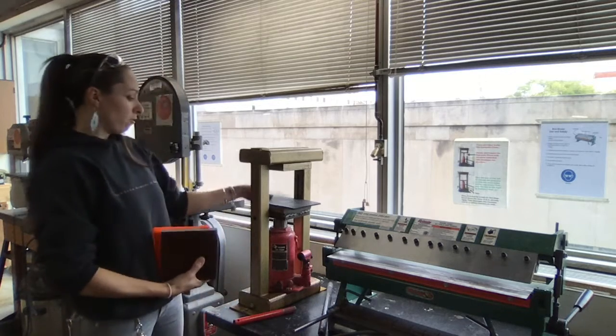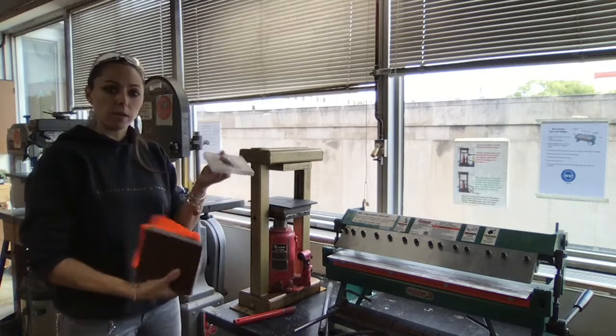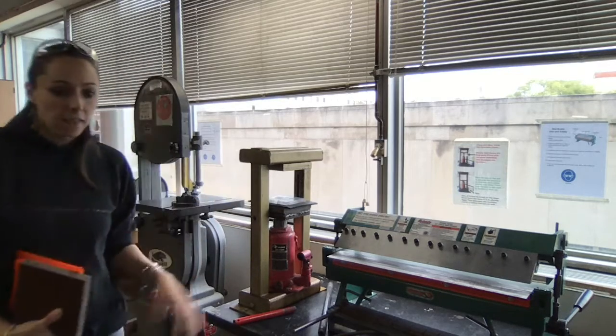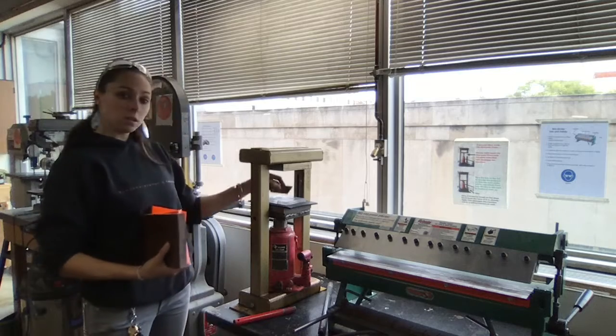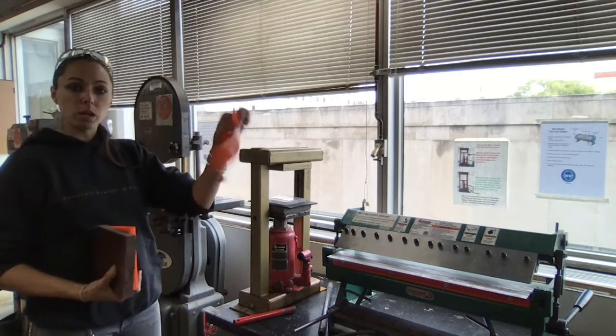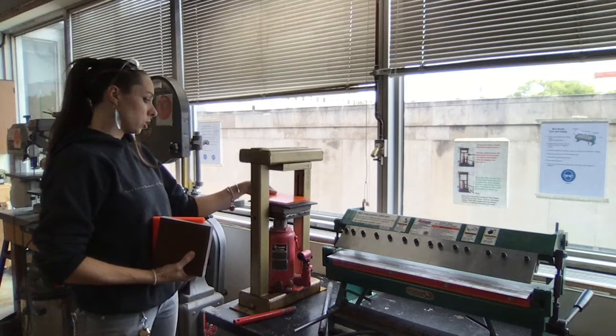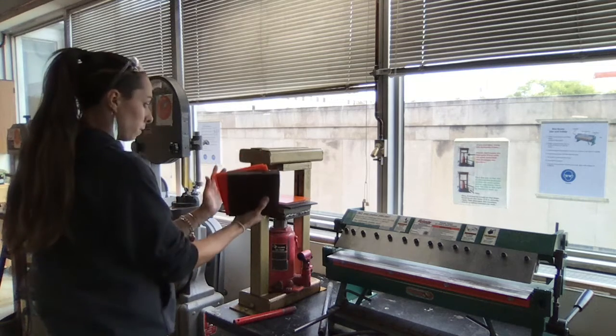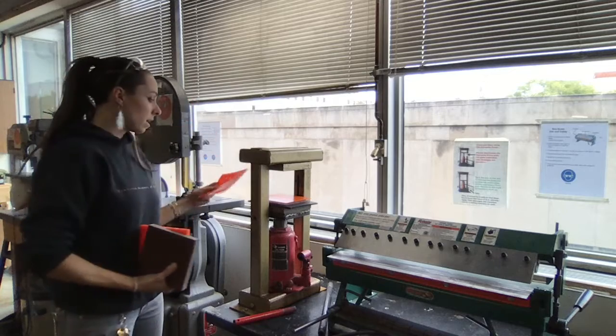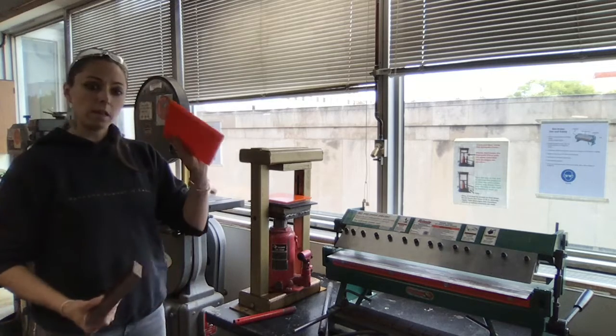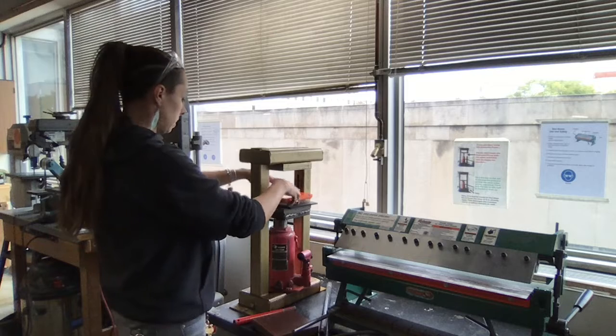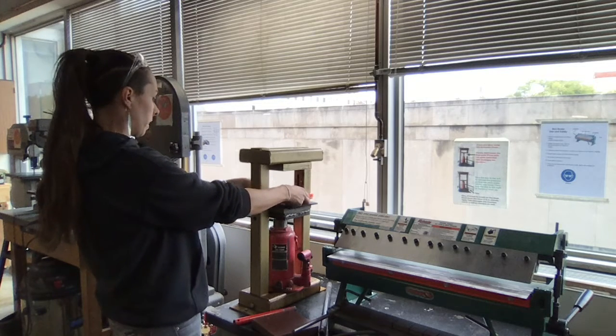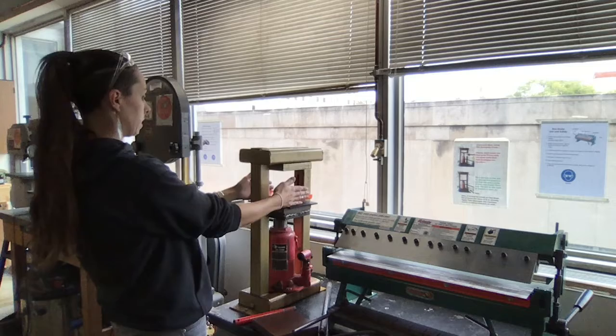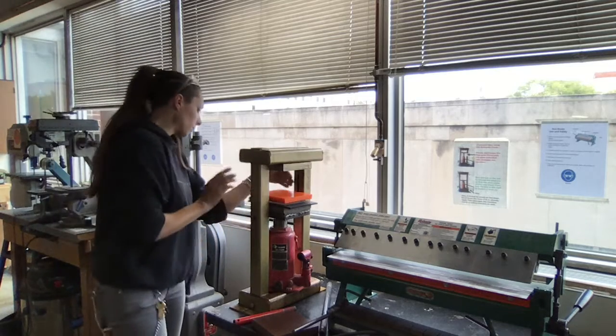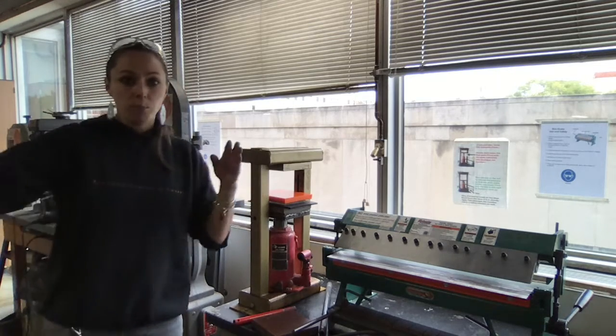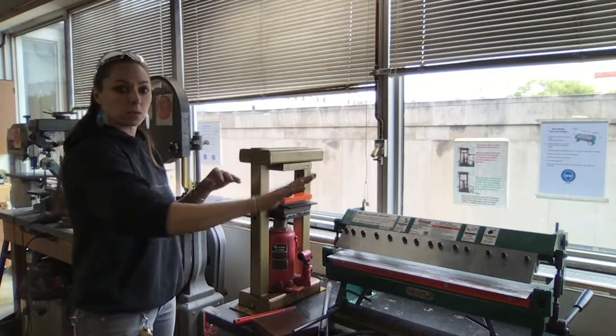So after I have my piece of recycled rubber down, I'm going to go ahead and put my die down. And then I'm going to put my annealed metal down. Then I'm going to put the 1/16 of an inch durometer down, and I want to make sure it's perfectly spaced in the middle. Then I'm going to put my 1/8 inch, then my 1/2. And this is another good time to always evaluate, is this in the center? Is everything lined up perfectly? You want to make sure everything is lined up. If it's not lined up, it'll slip right out of the press. It'll slip this way, it'll slip this way.